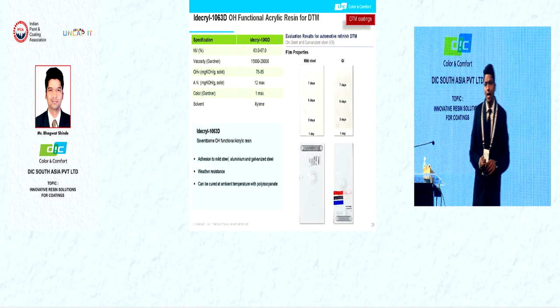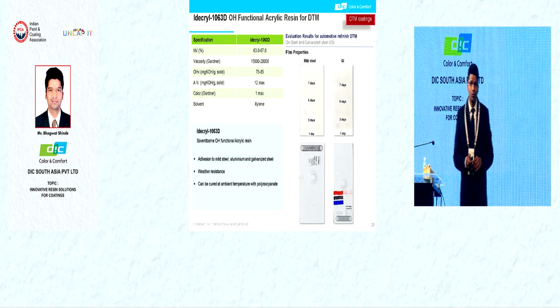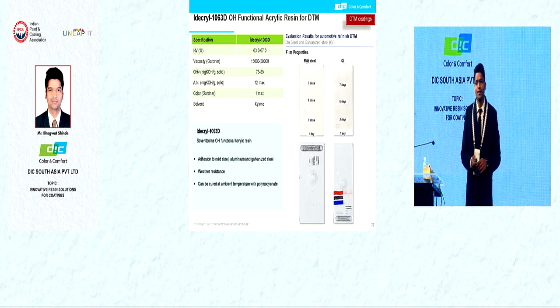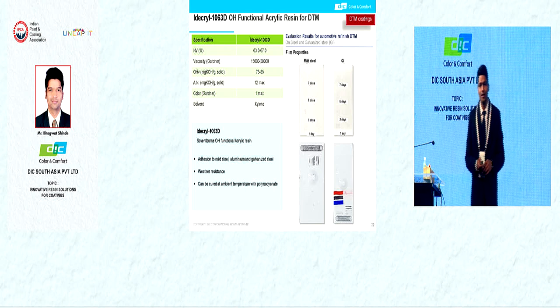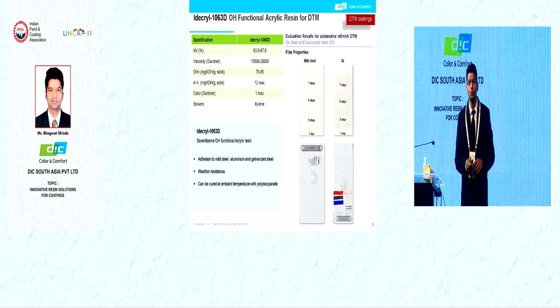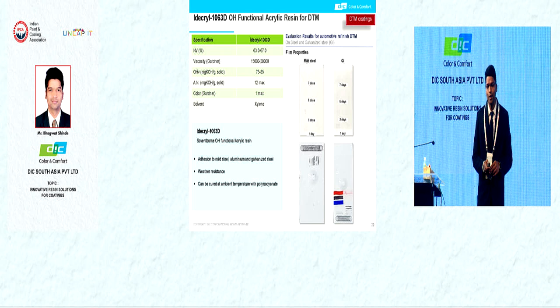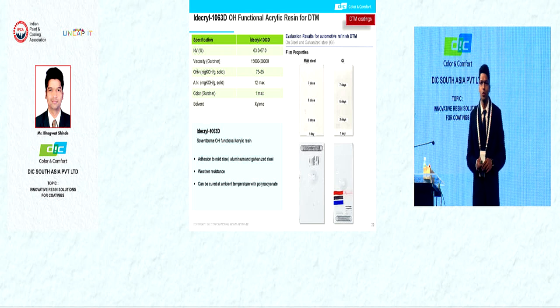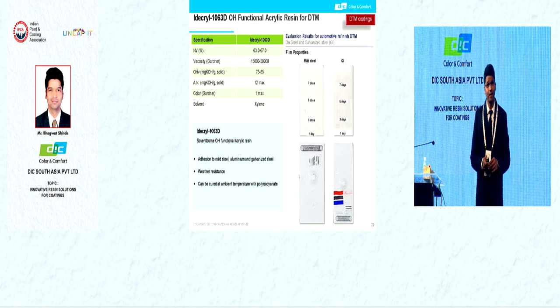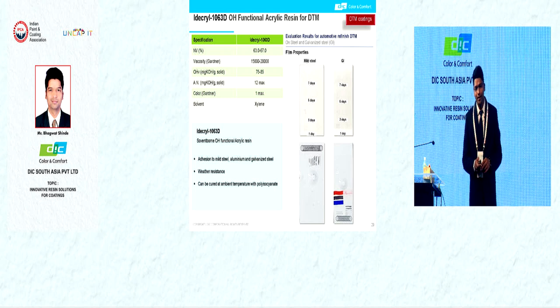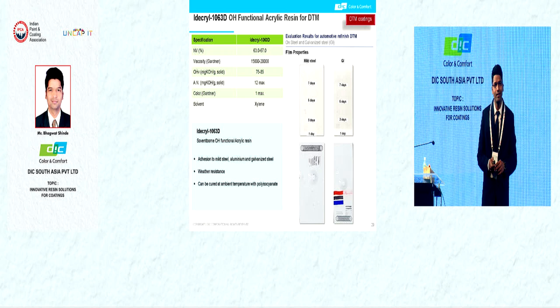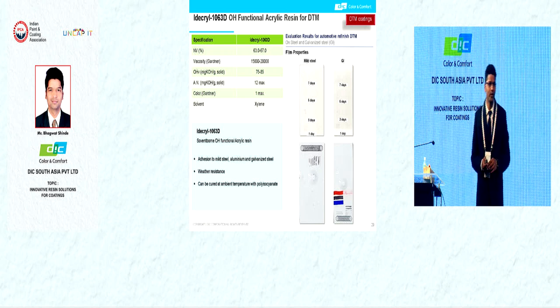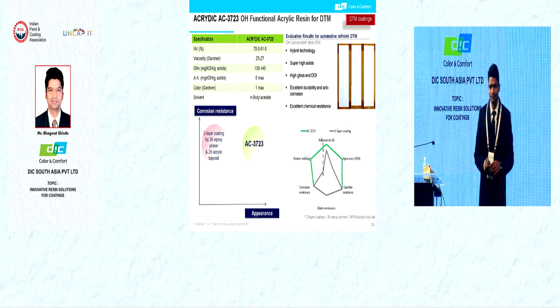So next one, I would like to introduce the 2K acrylic products for the DTM coatings. This is Idecryl-1063D. This product shows good adhesion to metals like mild steel, aluminum, and galvanized steel. This product shows a good weather resistance and can be cured at ambient temperature by polyisocyanate. This product has a hydroxy value of around 75 to 85, so we recommend this product for the economy segments.